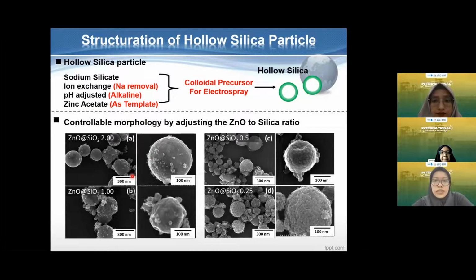Now, to produce the hollow silica, I adjust the ratio of the zinc oxide and silica particles from 2.0 until 0.25. So more silica particles. Here we can see that if there is a little amount of silica particles, there is not enough to cover... if you can see here, there are big particles, and at the surface there are small particles. The big particles here are the zinc oxide particles, and the small particles here are the silica particles. So I increase the amount of the silica particles from the ratio of 2 until 0.25.